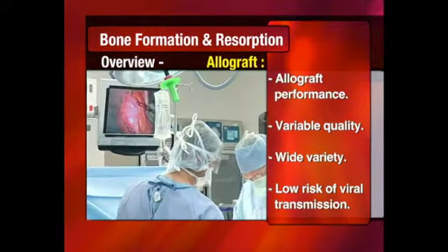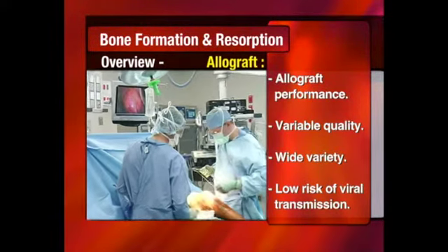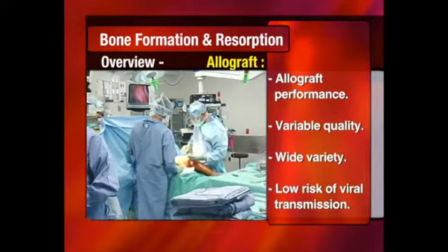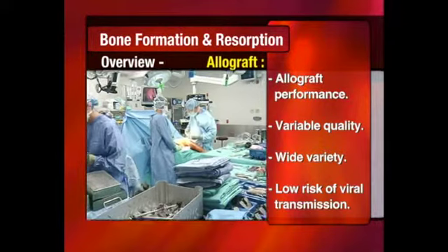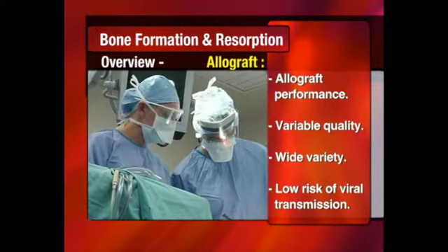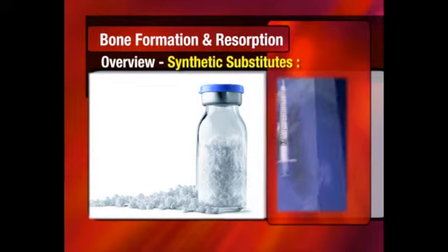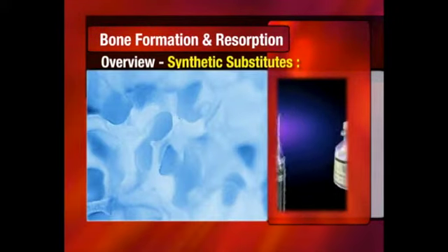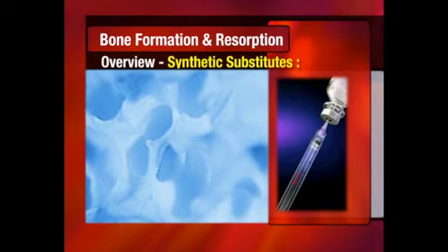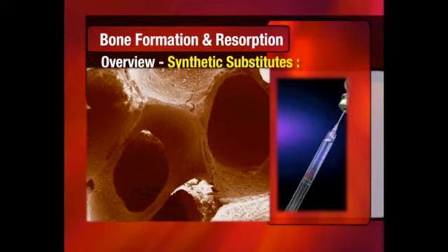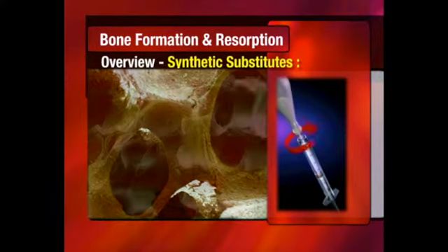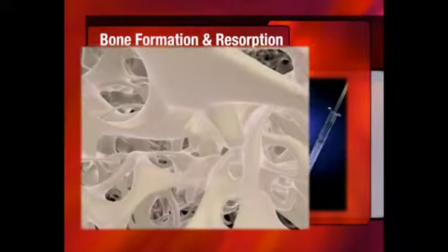Although the possibility of disease transmission is often cited with respect to bone allografts, it is estimated that the risk of viral transmission by unprocessed allograft is extremely low because of donor screening, about 1 in 2 to 8 million. Completely synthetic substitutes without a biological component have the advantage of laboratory synthesis with excellent batch-to-batch uniformity, and thus can be formulated to have specific handling characteristics, in vivo residence times, and variable delivery systems without the risk of disease transmission. However, completely synthetic substitutes rely on the body's local ability to regenerate bone, which may result in a poor outcome if this local ability is not ideal.